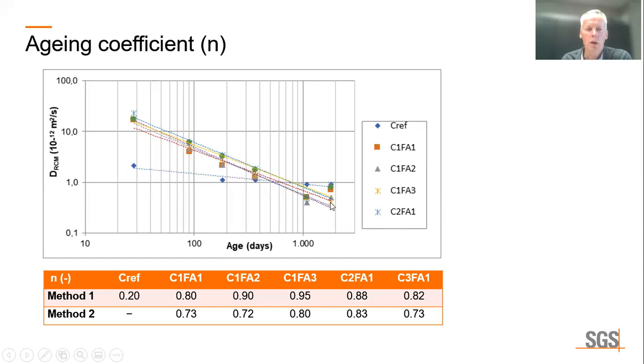So we have used a second method to determine the aging coefficient. For this method, we have used the K value from the linear relation between 1000 divided by TEM and the RCM value after 1 year.